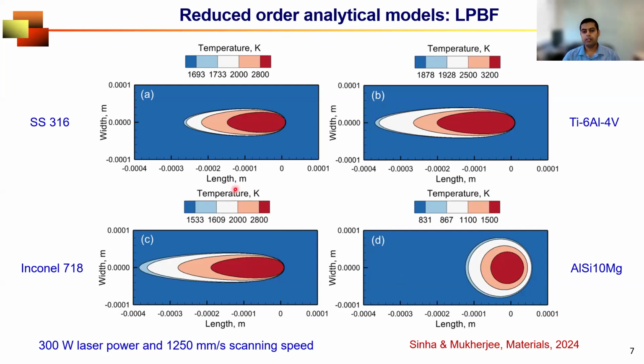And you see, depending on the differences in their thermophysical properties like density, thermal conductivity, specific heat, so on and so forth, they exhibit very different looking molten pool. And the temperature inside the molten pool is also quite different. So the advantage of these types of analytical models is they can not only provide useful insight of this process, but it can also be used for comparing different alloys in terms of their fusion zone geometry, cooling rate, evolution of microstructure, susceptibility to defects, printability, so on and so forth.